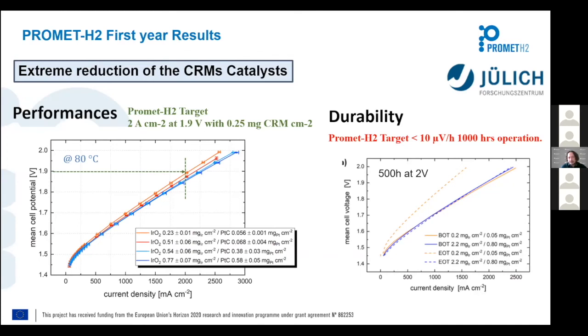Regarding the durability, of course, we have here a little issue. After a test of 500 hours, we can observe that when we have very low loading, that is the orange graph, we have a gap between the beginning of the test and the end of the test. This gap in durability, in performance, was not observed when we have a high loading. In this case, we compare 0.2 milligrams per square centimeter of iridium with 2.2 milligrams of iridium. In this case, we don't have this durability gap.